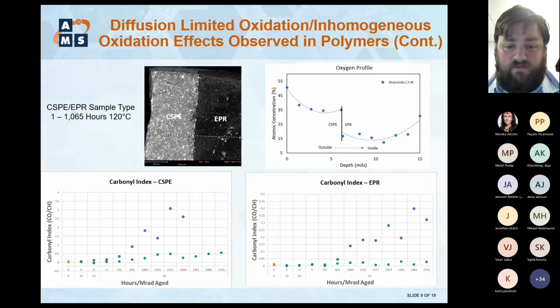And in this case, we have DLO effects, again, in type 1s, which is just the DLO effects from the normal insulation, but we also have inhomogeneous aging effects in the type 2s and type 3s from the jacket consumption of the oxygen and everything like that. And that's what we actually see in the carbonyl index values in the bottom plot.